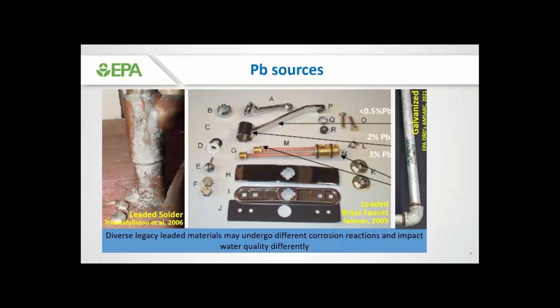The middle photo is showing you an older model of a leaded brass faucet, chrome plated. You can see the individual components of it, which do consist of leaded brass alloys ranging from less than 0.5% lead content to 2 and 3% lead content. Obviously, newer models are not allowed to have more than 0.25% lead on the wetted surface, but a lot of our houses and apartments, certainly mine, are older than the new restrictions, and we do have a lot of these old legacy brasses around.